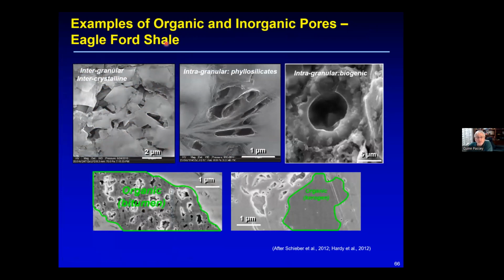Now, this is the Eagle Ford shale, and there's organic material, organic kerogen, that has no pores when it's low maturity, and when you get to higher maturity, and presumably it's bitumen, you get the organic pores. But in the Eagle Ford, you also have other pores that liquid hydrocarbons can go into.